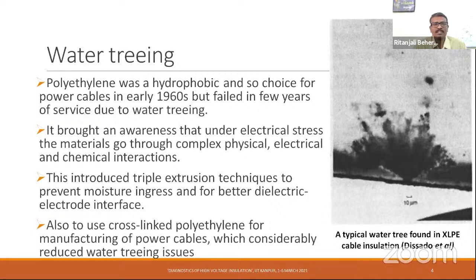Water treeing. I thought I'll spend only one slide on this. Polyethylene was hydrophobic, and so was a choice for power cables in the early 1960s, but failed in a few years of service due to water treeing. This actually brought an awareness to the researchers that under electrical stress, the material goes through a complex phenomenon, with physical, electrical, and chemical interactions. And this introduced triple extrusion techniques, primarily to prevent moisture ingress and also to improve the dielectric electrode interface. Because water treeing was found to be formed at this interface.